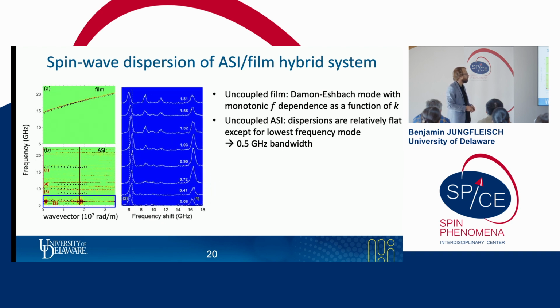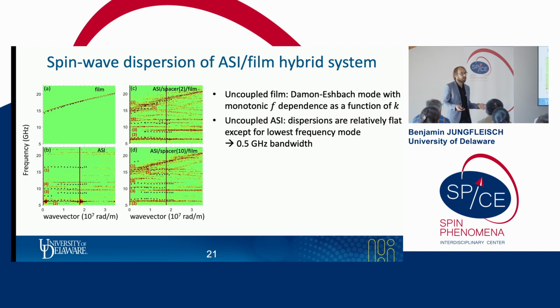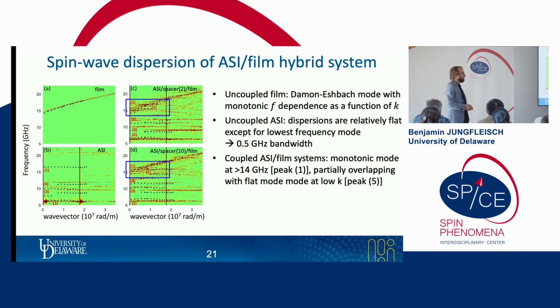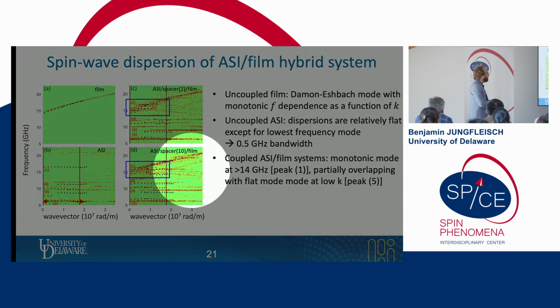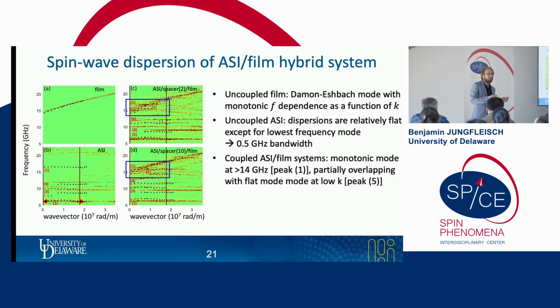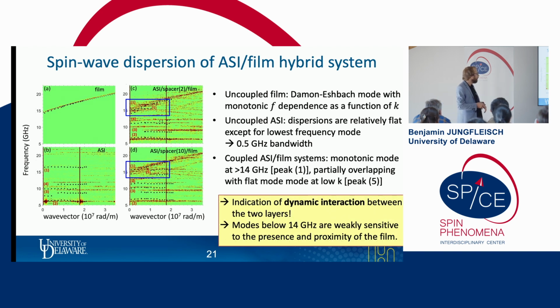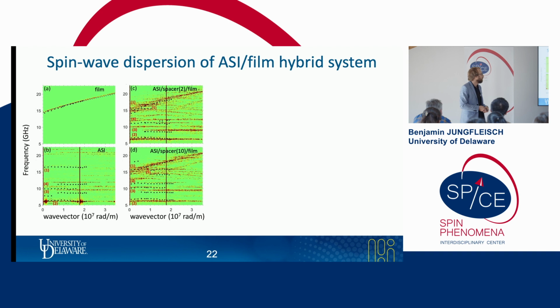So now let's compare this to the hybrid system with the artificial spin ice layer in contact with the film through a spacer layer. And we can now see here that the coupled artificial spin ice film system has a monotonic mode above 14 gigahertz, that's peak number 1. And it's partially overlapping with mode number 5. And from both the experiment as well as the simulations, we cannot conclusively tell whether these modes are actually hybridizing in energy. So we see here the indication of dynamic interaction between the two layers, and the modes below 14 gigahertz, below the Damon-Eshbach mode, are only weakly sensitive to the presence and proximity of the film.